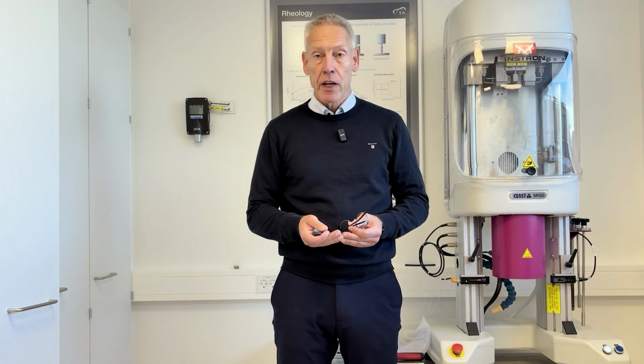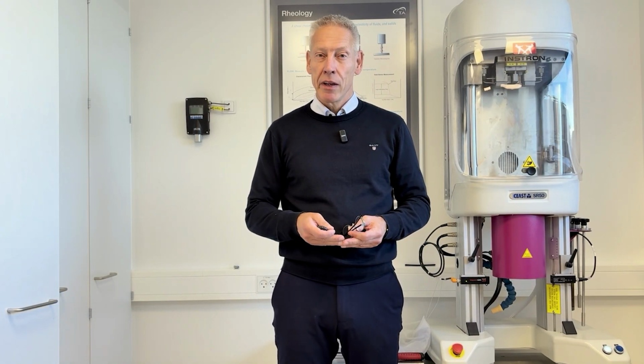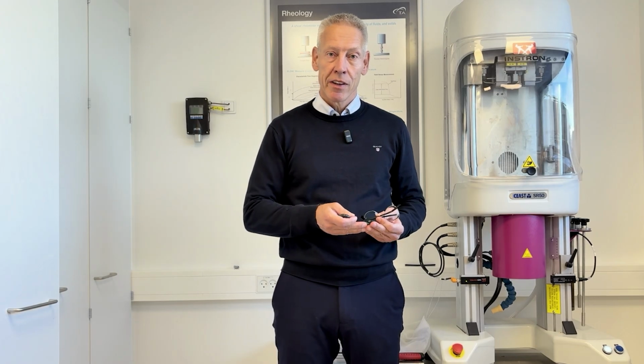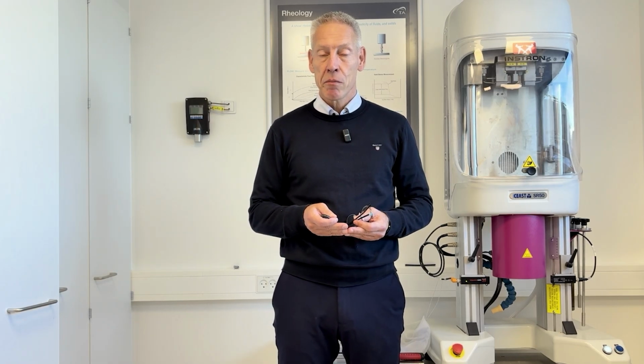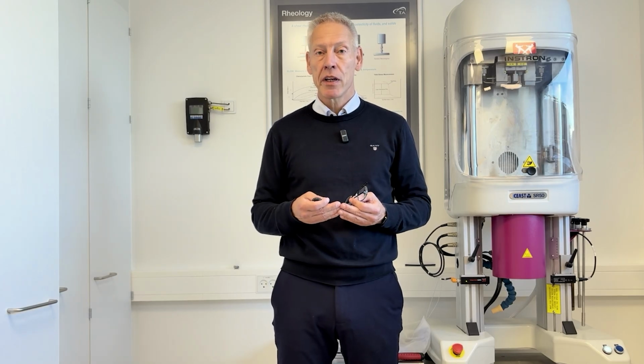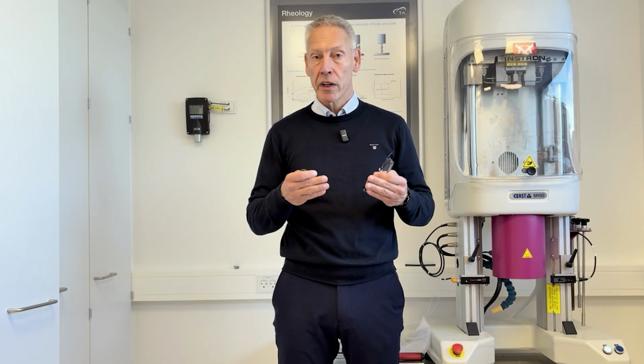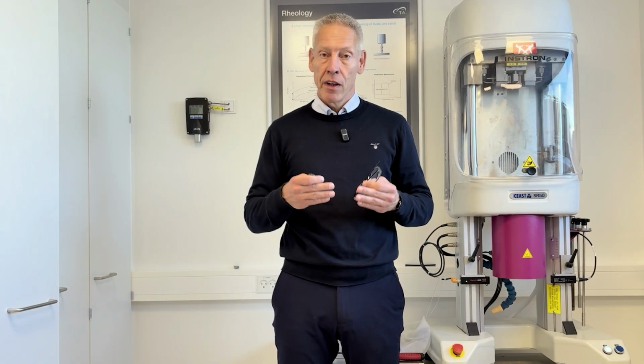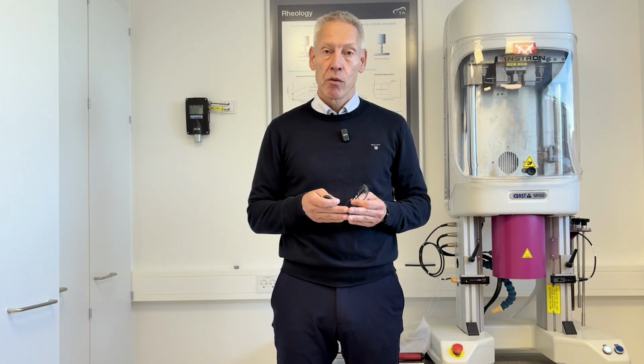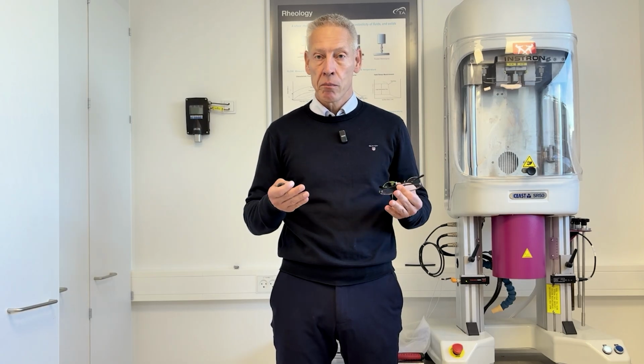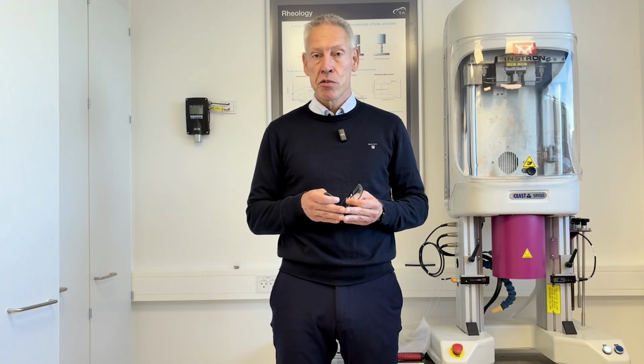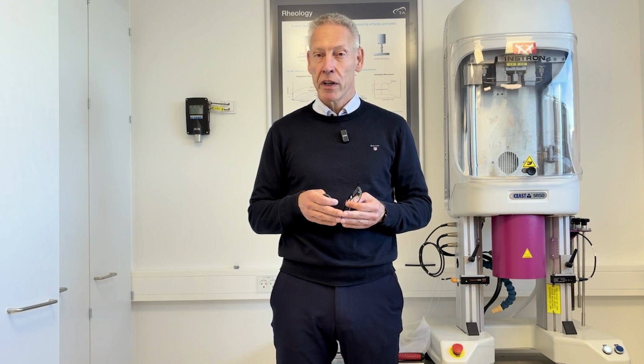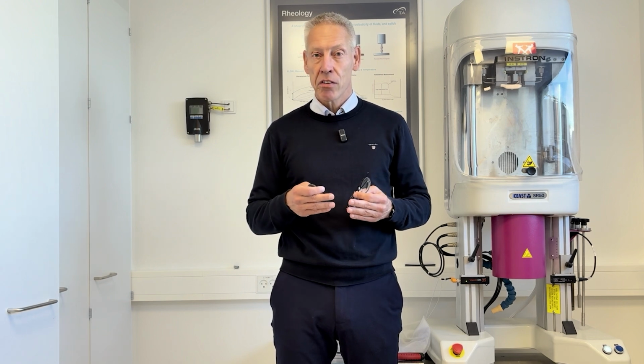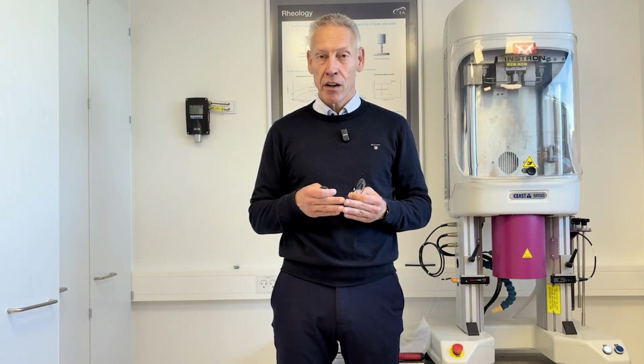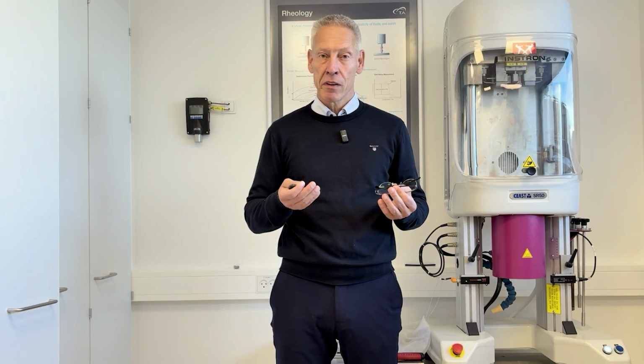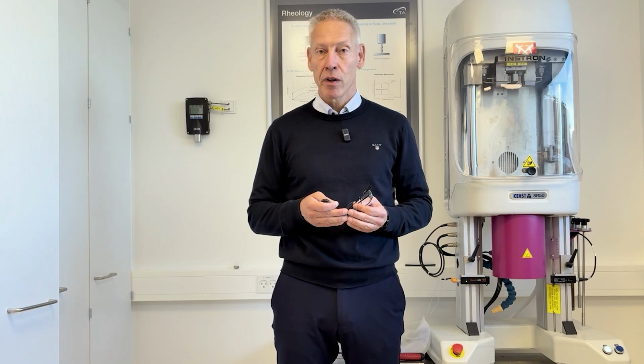We are now in the rheology lab. Polypropylene can be in a solid state or it can be in a liquid state. If you melt the polypropylene, then you have something where the behavior is dominated by the chains. So different molecular weights, different additives, and so on are what gives the response of the melt. So performing experiments on the melt state actually allows us to see into the material to understand what is the molecular weight distribution, are there any interactions, what is the mesh size, so we can gain a lot of very interesting information about the chemical nature of our materials by rheometry.